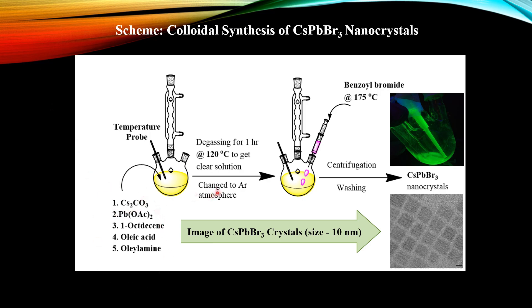When all things are mixed and taken to a high temperature, the bonds of the corresponding precursors are broken and there are free ions in the solution. Then we change the environment to an inert atmosphere containing argon, and we proceed with adding the further precursor, benzoyl bromide — this is the bromine source. After centrifugation and washing, we get these bright nanocrystals which look green in color, with a typical size of around 10 nanometers.